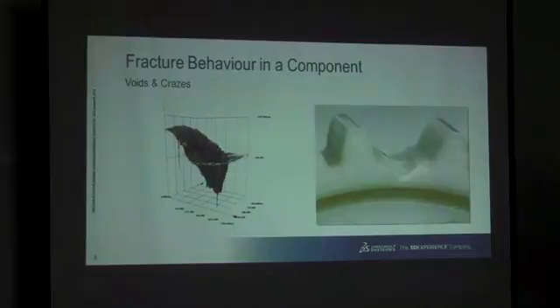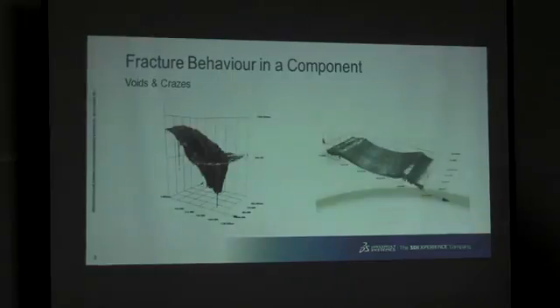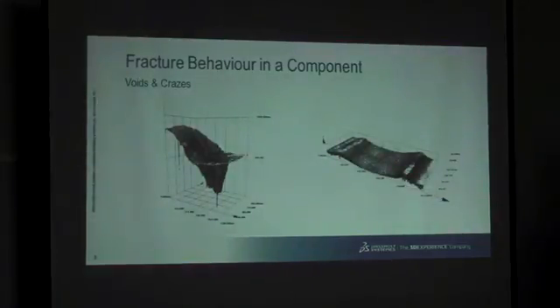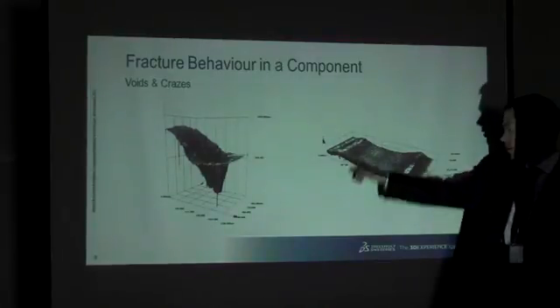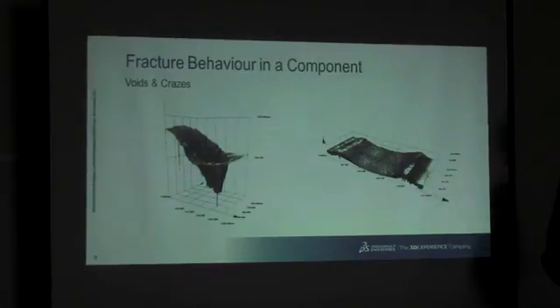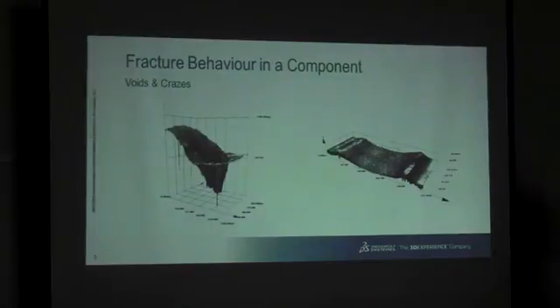So that's a typical void. On the right-hand side, you see a failure where basically a tooth has broken off from a gear wheel. This is a typical craze failure. And when you look at that surface, or that fracture surface, this is what you have, which is pretty logical, following the actual mechanism. The craze opens up, and then it opens up on two sides, and then it just goes through. What's important with both of these, the material in itself is highly ductile.